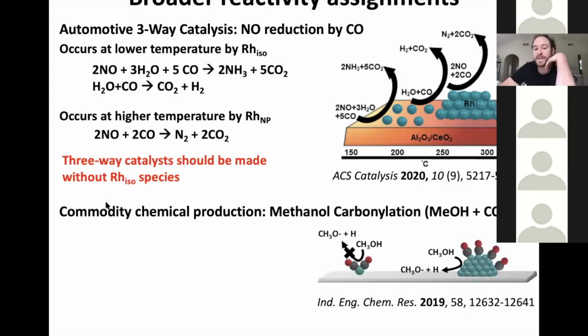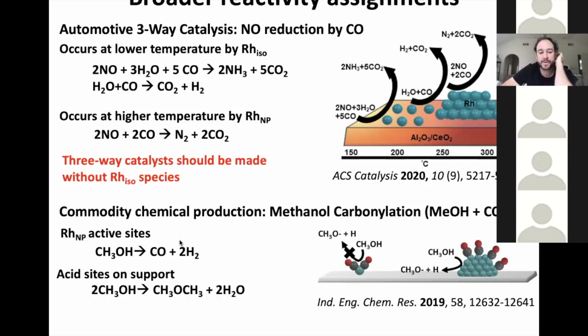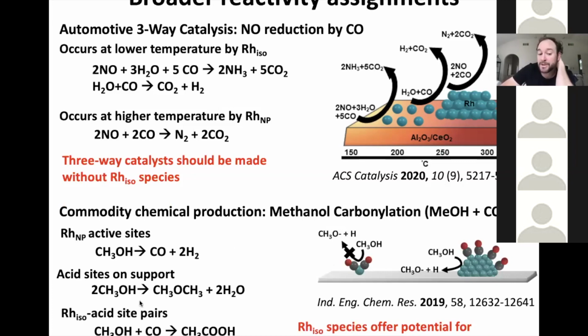We've done this in other cases looking at commodity chemical production, so methanol carbonylation, which is done now using homogeneous catalysts in industry. We found that rhodium nanoparticles cannot be used to do this chemistry because they'll just decompose methanol into CO and hydrogen. Acidic sites on a support actually drive a dimerization of methanol reaction to make dimethyl ether, which is also not what we want when you're trying to do methanol carbonylation to make acetic acid. However, we found if you could make pairs of sites between isolated rhodium species and acid sites, you could make some acetic acid. And so in this case, isolated rhodium species seem to offer some potential for heterogeneous methanol carbonylation. So I went over this just to tell you it's important to develop rigorous structure-function relationships.